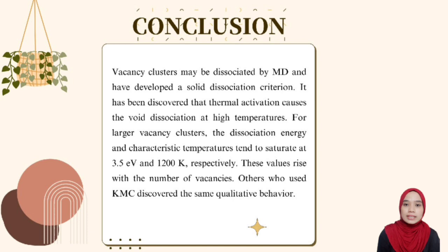For larger vacancy clusters, the dissociation energy and characteristic temperature tend to saturate at 3.5 electron volt and 1200 Kelvin respectively. These values rise with the number of vacancies. Others who used KMC discovered the same qualitative behavior.